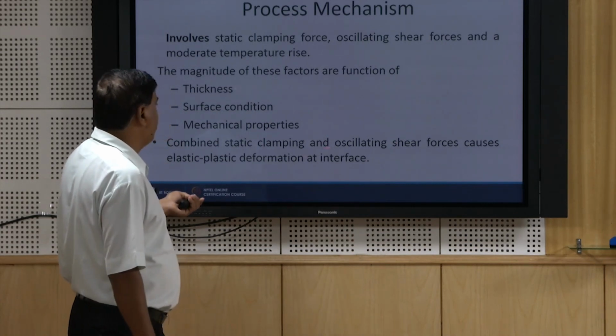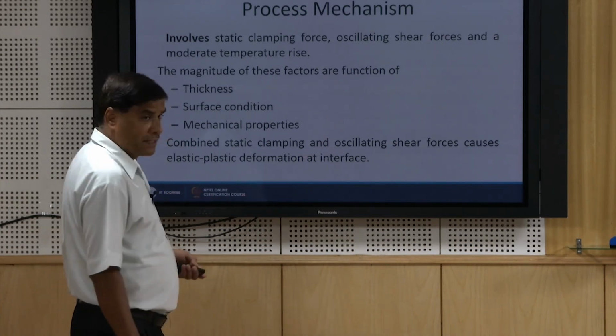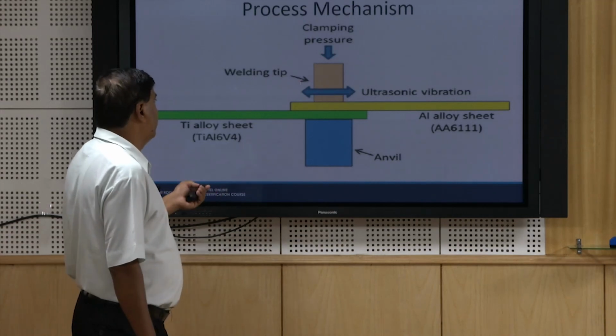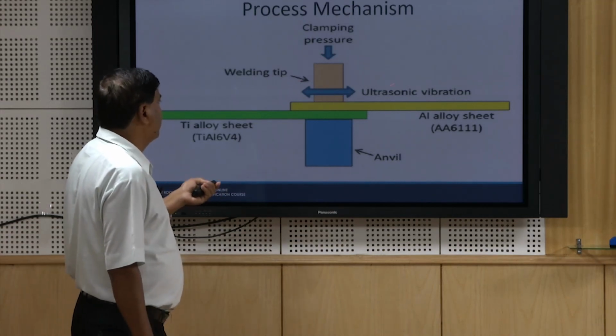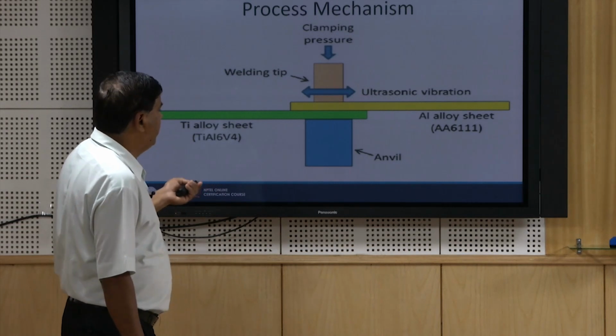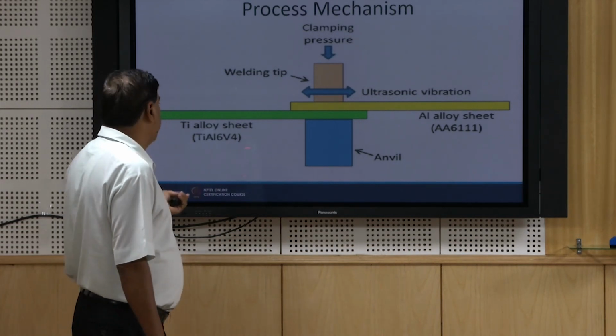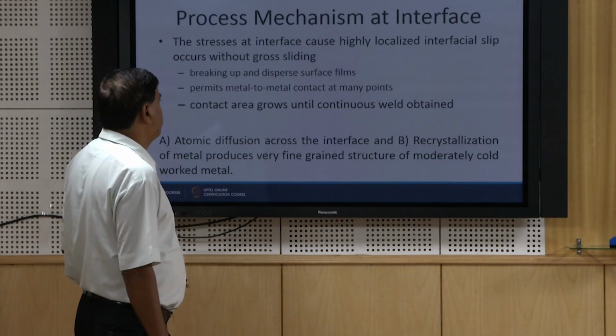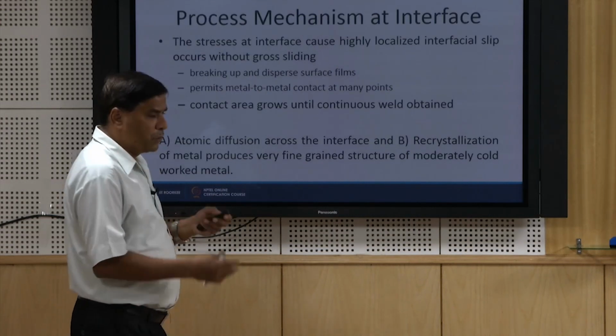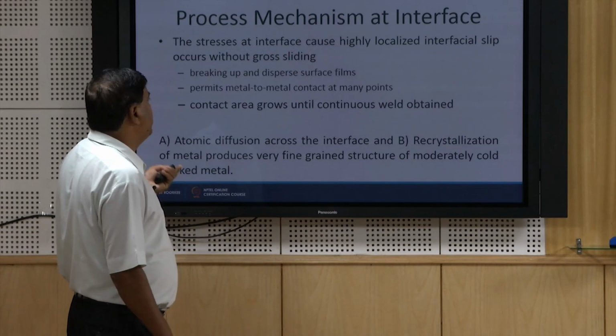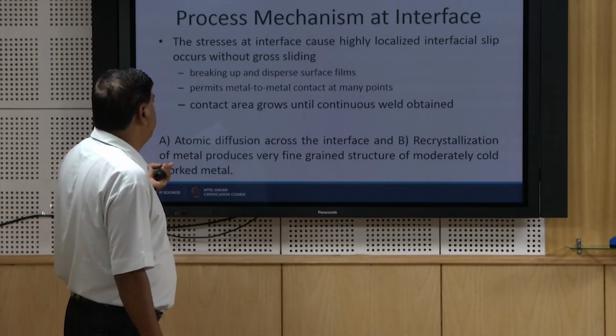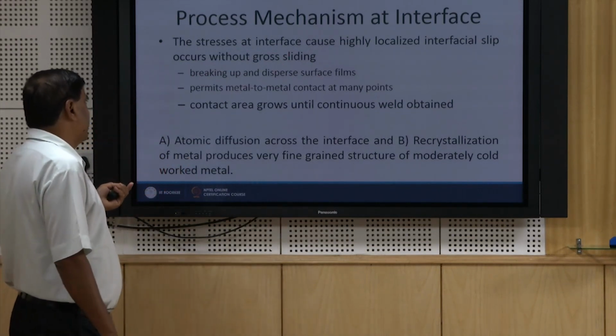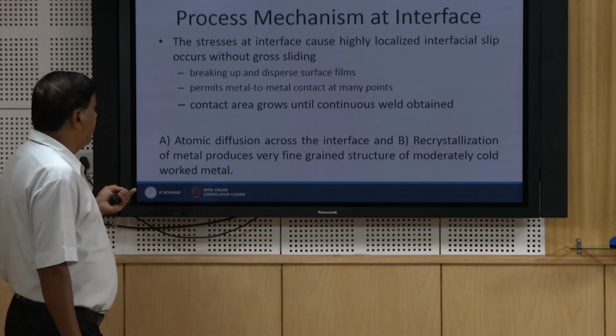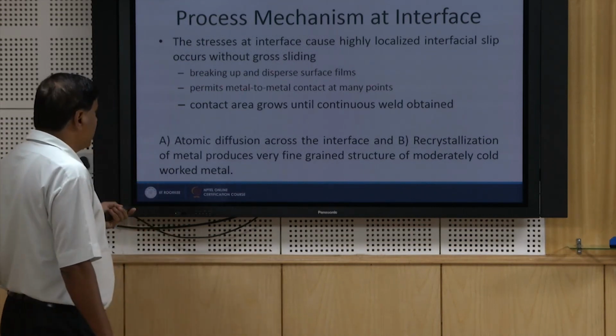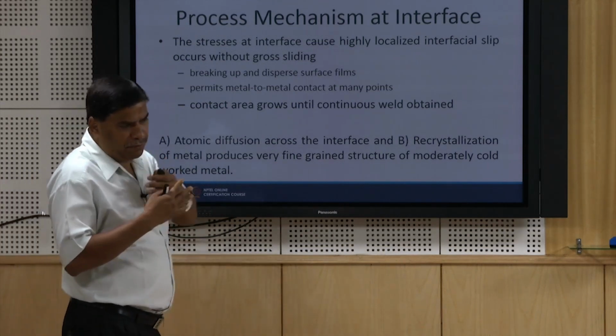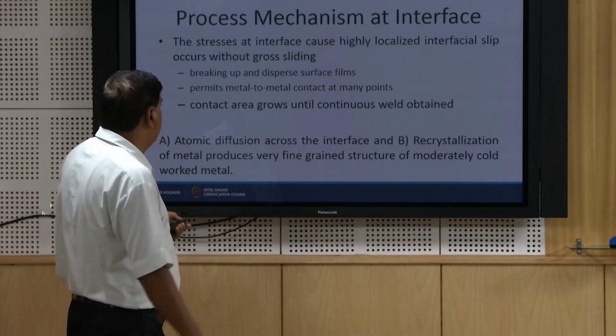So, the combined clamping and oscillating force causes the elastic plastic deformation at the interface. This is what we can see, the clamping force and the ultrasonic vibrations appearing in the form of lateral shear force, and the two sheets are welded and the samples are supported over the anvil. So, in the course of the process, what happens? Initially the contact at the interface breaks the surface films and oxides, disperses them, and metal to metal contact is established. Gradually the elastic plastic flow of the material at the interface continues,